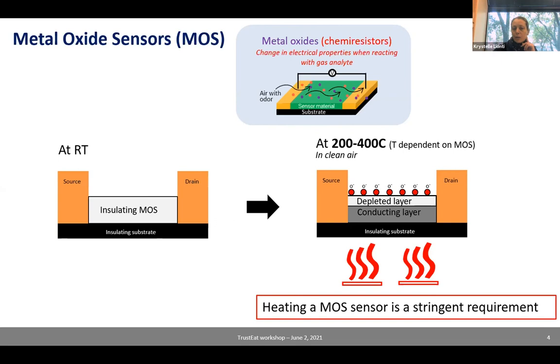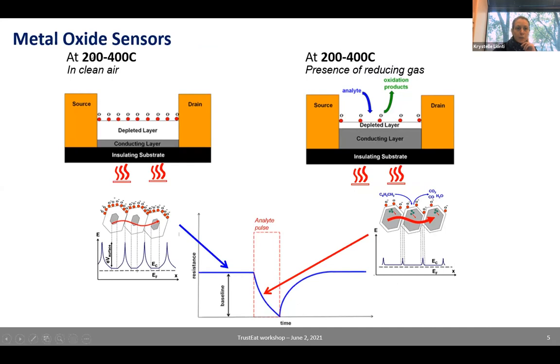And so what's going to happen is that oxygen from air is going to like to bind on the MOS surface, just because oxygen is very electronegative. And it's going to steal some electrons from the MOS layer and create a depleted layer at the surface. So on that slide, the state here on the left is the same state I was talking about. It's our reference state in clean air. If we look at the resistance of the MOS, it corresponds to baseline resistance.